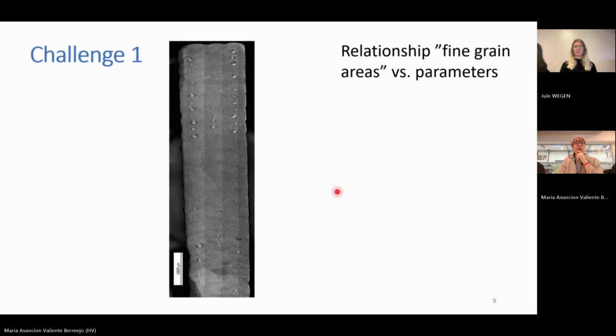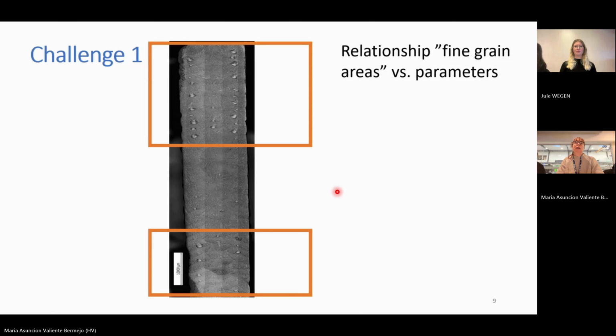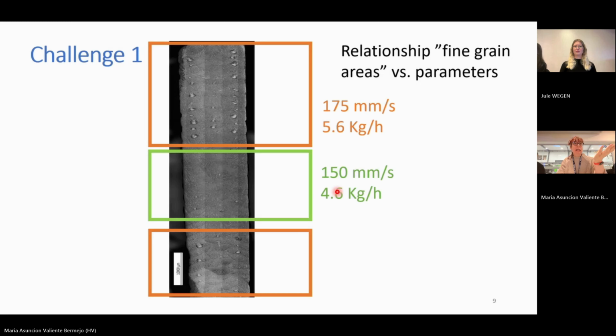Then we realized that there was a relationship between the presence of these fine grain areas and the parameters that we were using. This is just a cross section, but we were using different parameters. As you can see, with just this cross section and an optical microscope, we could easily see that there was more concentration of these areas than when we were reducing the wire feed speed and the productivity, let's say, the amount of kilos per hour. So we found that there was a correlation. Something is happening in the process and the microstructure. We need to find out what's happening.